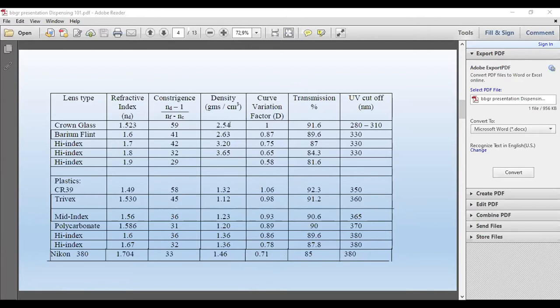For crown glass 1.523, you are losing 8.4% just due to reflection. So out of 100% of light that is entered, you're losing 8.4% just due to reflection. I'm ignoring absorption because absorption doesn't really play a part with lenses so thin. So this is only due to reflection. Now, the higher the index, the less the transmission and more the reflection.